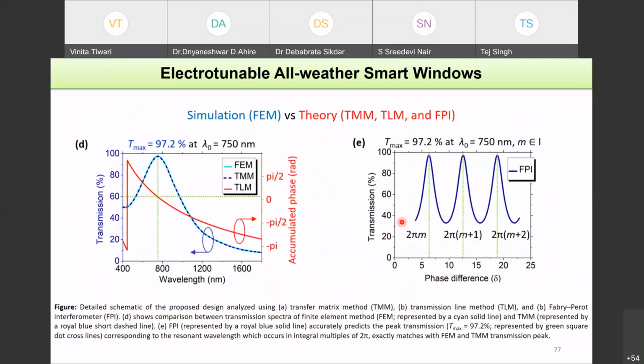So this is how I show the results. What we calculated from FEM, which is the light blue line, and the transfer matrix method, they are perfectly matching. The transmission line theory is also giving you the perfect calculation of the resonance peak position. It means that whatever theory or structure we are simulating and designing is backed by both simulation, theory and sometimes experiments. So these electrotunable devices are possible, and this is the possibility to take them further into the field of high-speed optical communication, where tunable devices can find more and more applications.